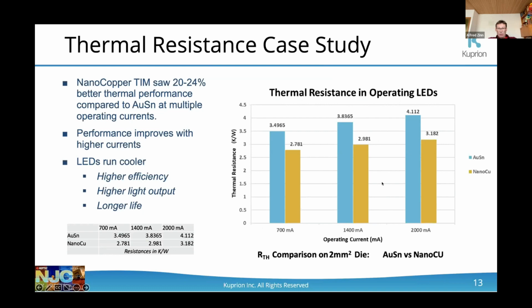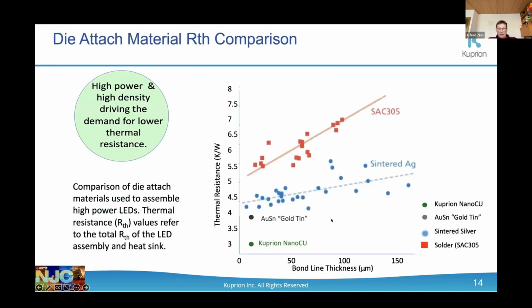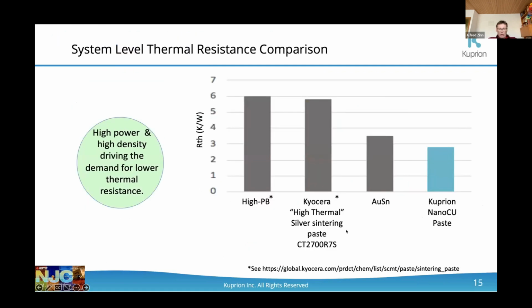It shows how much better the material is because you got bulk copper with much higher thermal conductivity than the gold tin solder. So very nice results. So further, when you compare it to the other materials that are out there, so we plotted here published data from SAC 305, sintered silver, our gold tin we tested, and our copper. So we're thinner bond line, which is really important for the heat transfer, and just much better performance. Here's another comparison, high lead solder, high thermal sintering paste, gold tin solder, and our material.